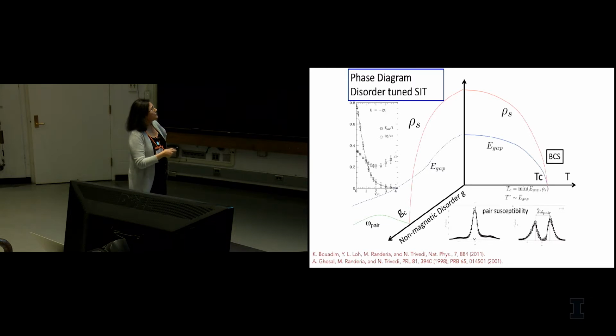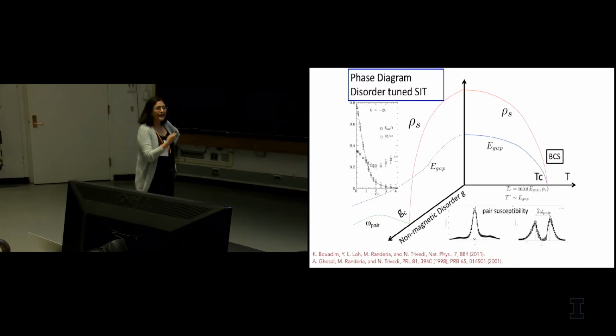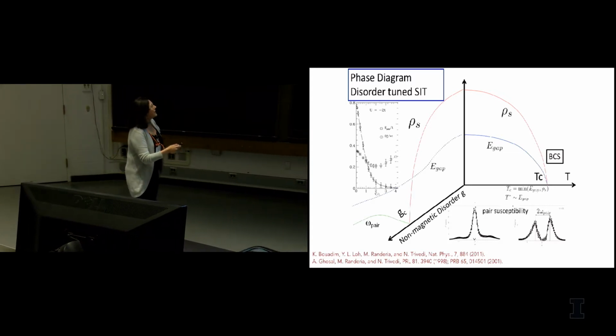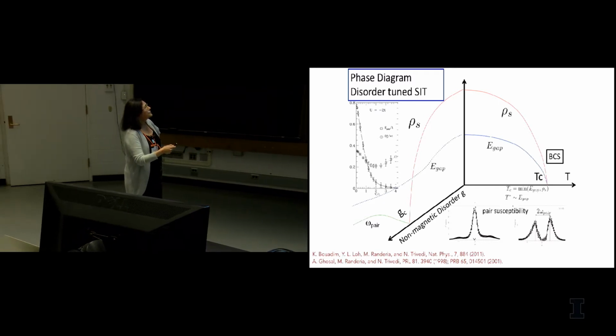You might have expected to find the Anderson localized paradigm at large disorder, but that's a singular point. So the presence of any attraction opens a gap, and that remains finite. The superfluid density still vanishes at some critical disorder and crosses the scale, the gap scale. Usually it's a very large energy scale on the order of EF, but it crosses that and vanishes at some critical disorder. And in this region here now, you would basically open up a pseudo gap.